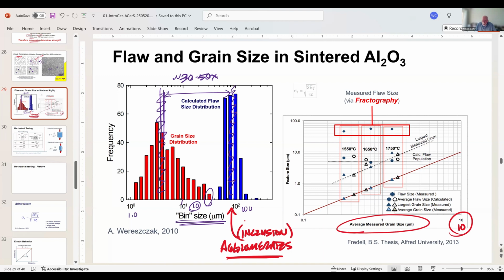So you can see that the measured grain size on average is here. And this is showing us that as I go up in temperature, as I increase my temperature, I increase the size of the grains. Not a surprise. But when I look at this, the largest measured grain is here, and this set of data shows that this is my range of grain size. But if I were to look at it this way, so I get size versus frequency, and much like I have over here, I would have this distribution, which we would argue is log normal.